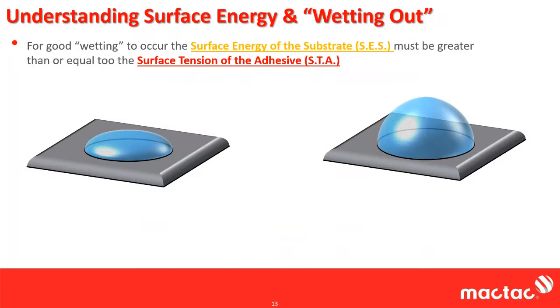On the left, what this is representative of is a polar material. It's a material with a lot of polarity, as we discussed before, a lot of charge there. So you've got a lot of force working on that adhesive, spreading it out. On the right, though, you have something that doesn't have a lot of polarity, something that doesn't have a lot of net charge, like we discussed before. And so the surface tension of the adhesive is really working to pull it together.